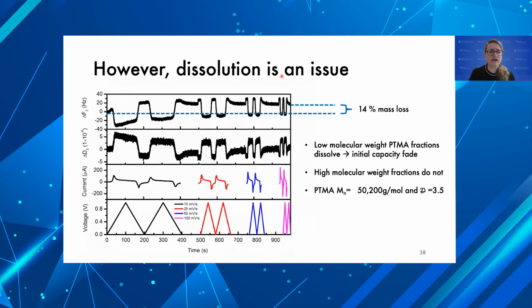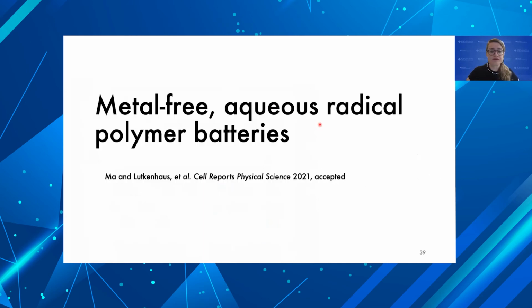However, I wanted to point out to you that dissolution is an issue. We see a drift in the frequency, which corresponds to a 14 weight% mass loss. I don't have time to tell you about it, but I just wanted to indicate that this is a common problem for many redox-active polymers. In other work that we've published, you can solve this issue by simply cross-linking the polymer, and also by adjusting the electrolyte that you choose. So it is a problem that can be solved, and you can see our follow-up publications to this one in which we do that.